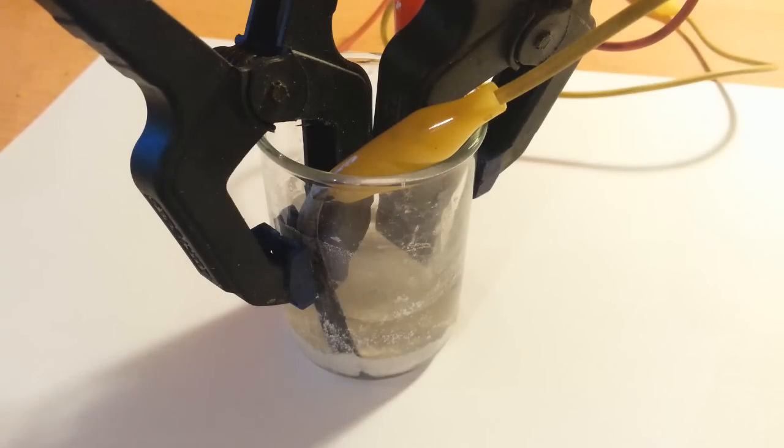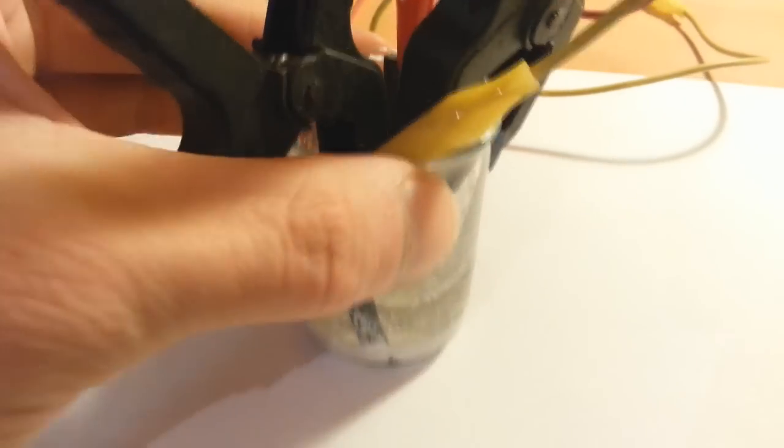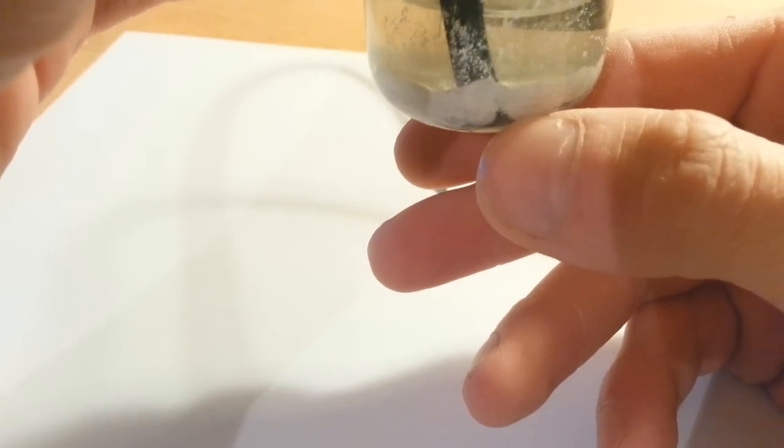I recharged this for about 20 minutes because I charged this battery at 1.4 volts and 100 milliamps. You can see right here the zinc oxide transformed into zinc.